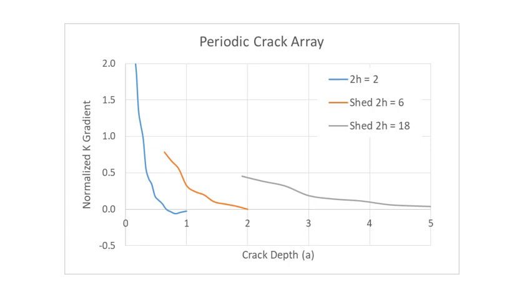Now, I have to say that that's not the whole story, because we do know that stress corrosion cracks will fail occasionally, and there are a couple of reasons for that. The first is the cracks may well find themselves in a domain where fatigue becomes an issue, and secondly, and from my perspective here more importantly, at this point we have not considered the effect of having a finite width of pipe wall that we're propagating into. That will be the topic of my next video.